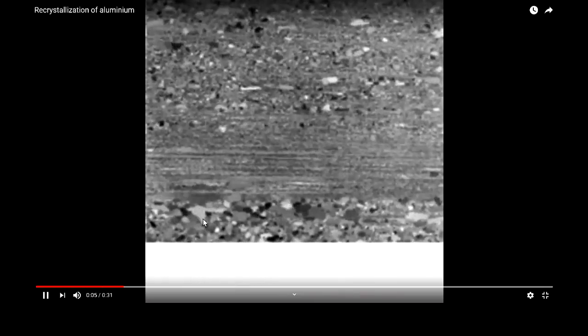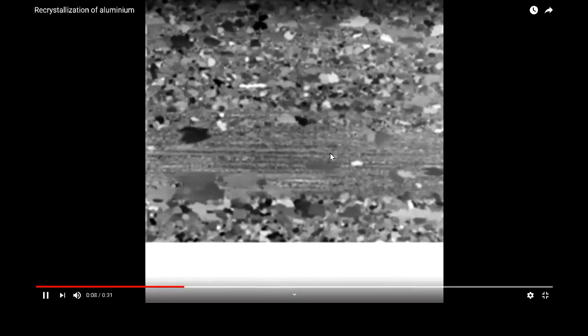So what we have here, again, under a microscope, in our SEM microscope, we can use heated stages. For recrystallization to occur after deformation, we need energy, we need heat to get those atoms moving again. So what you can actually see in this image here, probably a little bit poorly, we see directionality going across like this. That's our rolling direction. So our material is being squashed in this manner from going through rollers repeatedly. We've got some very, very fine, tiny little grains. We can't really resolve them in this image because they're very tiny. As we apply heat to our sample, we can see straight away we've got grains starting to grow. They're nucleating and growing. And they usually nucleate and grow from interstices in our grain boundaries.